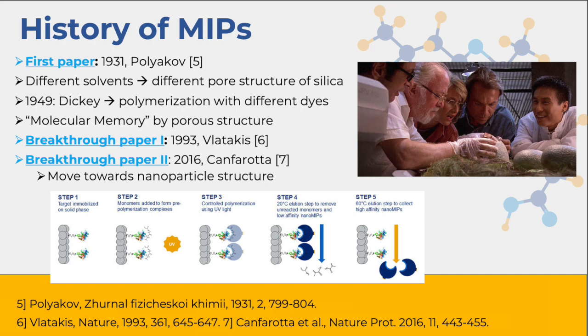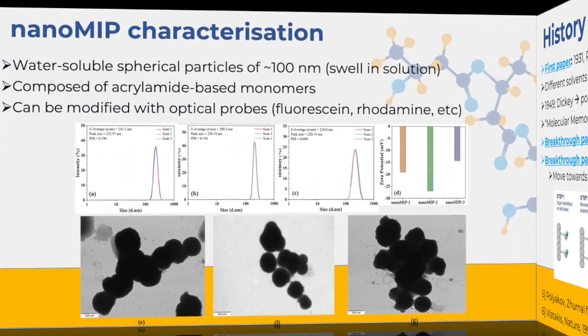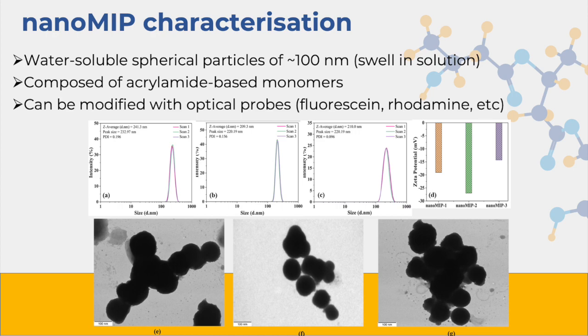Several approaches have been developed to increase the affinity of molecular imprinted polymers. One example is using a solid phase imprinting approach to produce nanoparticles. We work with a range of monomers, typically acrylamide-based, which can be adapted — for instance, with a tertiary butyl group for hydrophobic interactions — in order to cover different non-covalent interactions. In this solid phase approach we typically use NIPAM, which swells, and use a series of temperature elutions to get the best high affinity materials. There is quite a range in size, typically anywhere between 50 and 150 nanometers, and they are spherical.